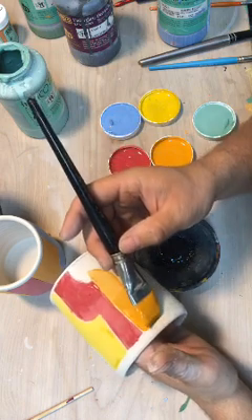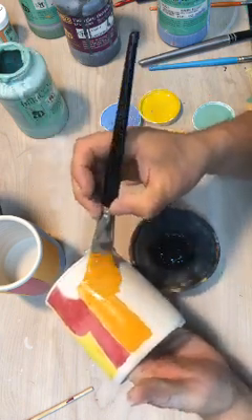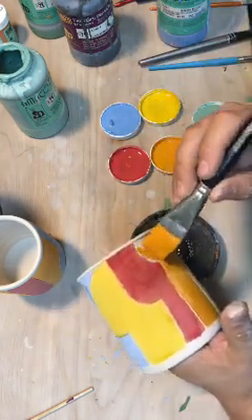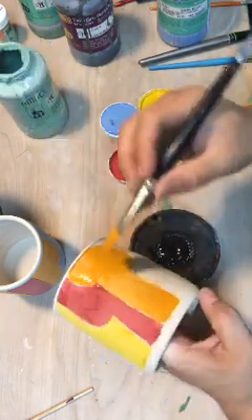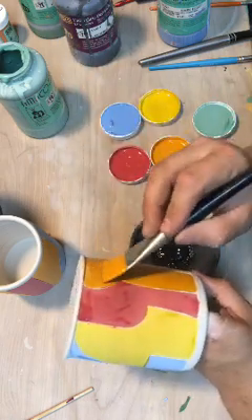Nope, these will not be clear glazed. They're going to be left the raw underglaze. But fired to cone 10, they gloss up themselves. And I'm going to put some stain on them. And that stain has enough flux in it that it'll make sure that all these get enough of a glassiness to them that they're durable.